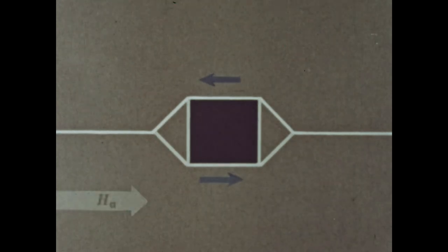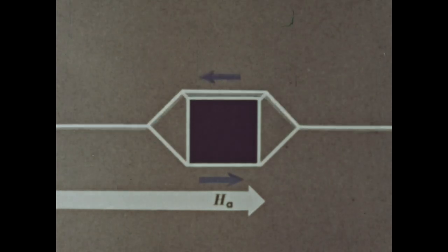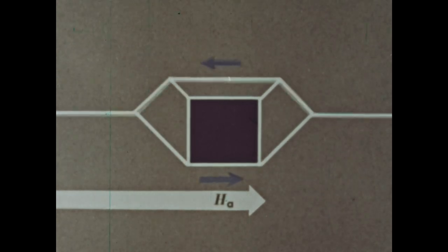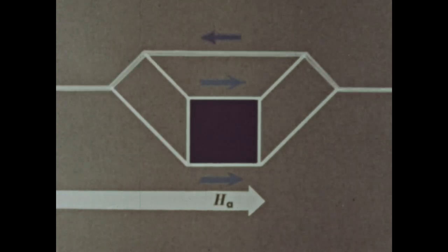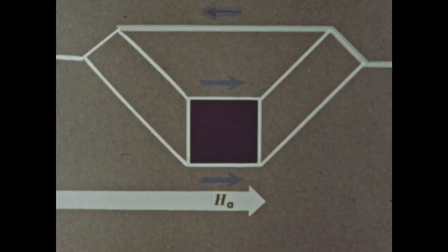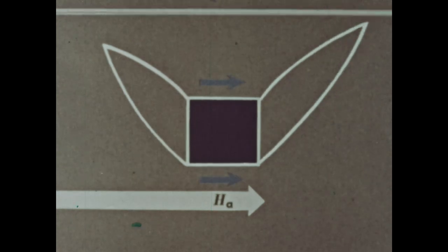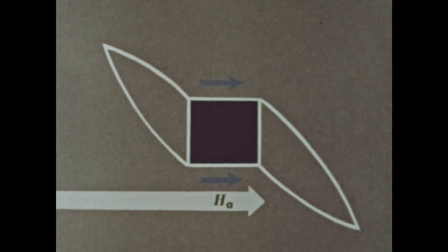However, under a steady field of sufficient magnitude, the secondary domains are stretched out until their wall areas have increased so much that a decrease in total energy is possible by the introduction of some magnetostatic energy. At this point, the primary domain wall breaks free, and the secondary domain walls shrink and close together. The resulting spikes stabilize, as before, with a minimum total wall and magnetostatic energy. Because of strains or other imperfections, a spike may swing around to a position of maximum stability.